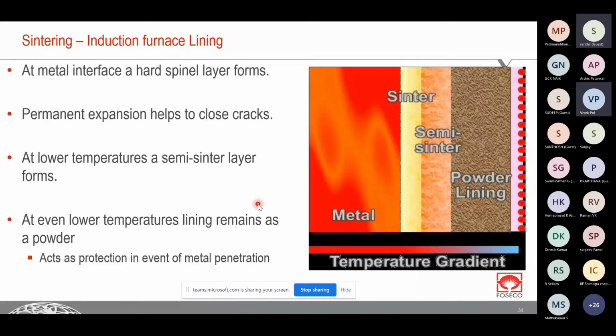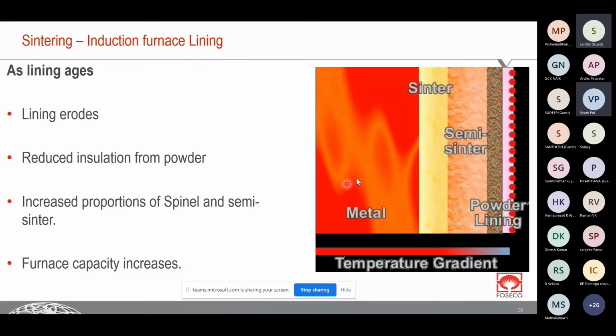When the lining becomes old, then the powder form becomes smaller. But if your furnace lining condition is good, the measure for that is when you break the lining, there should be a situation like this. You must have material in powder form at the backup, then semi-sinter form, and then sinter form, which is the metal facing area. So obviously lining erosion is more when the lining becomes old. But this powder form should always be there.